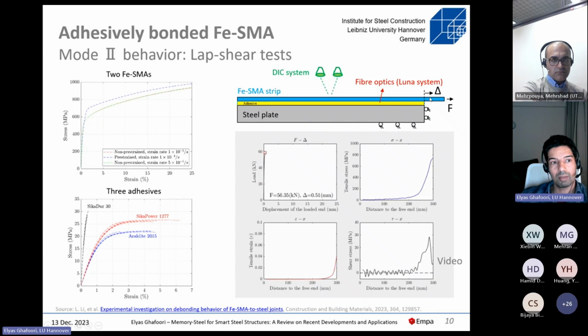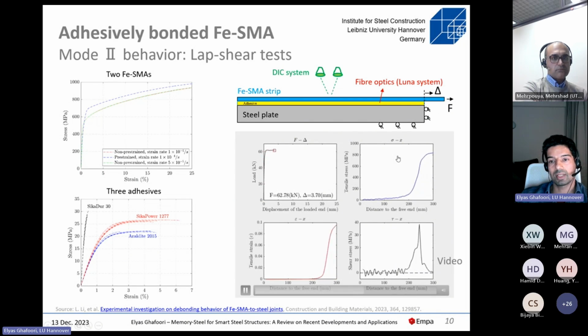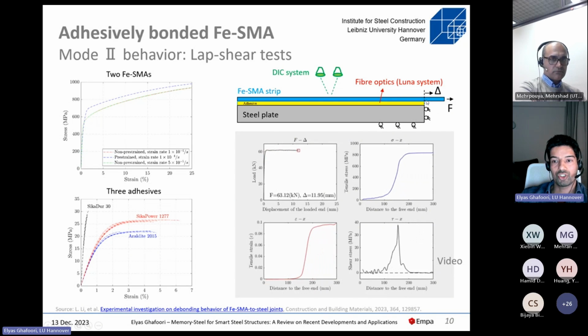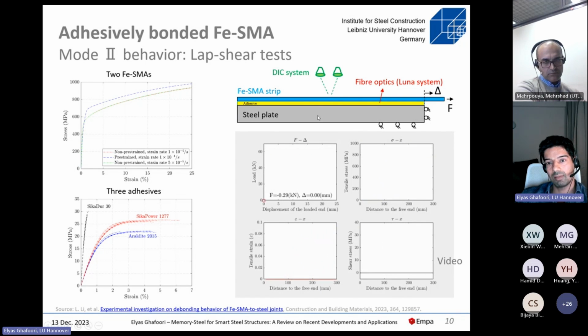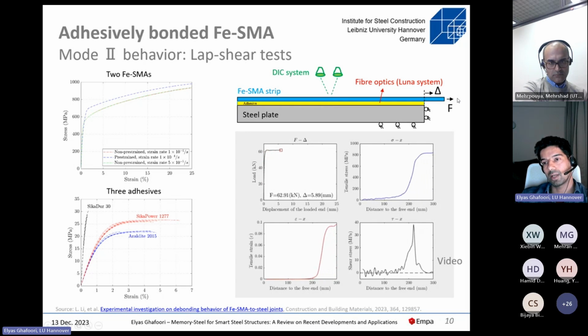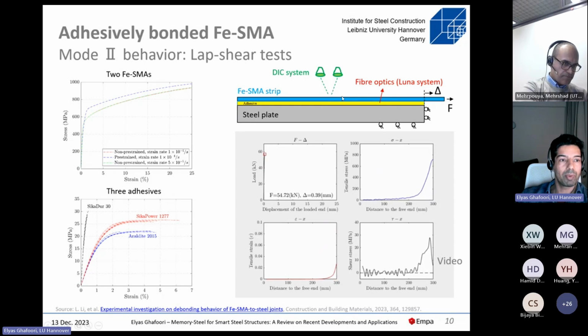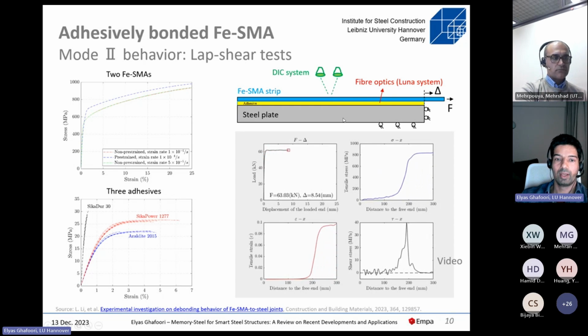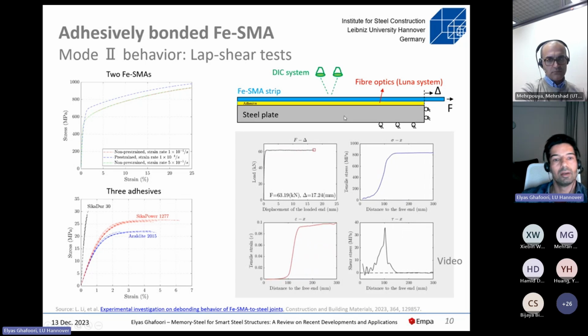Of course, the bond is very important here. So we have done extensive tests on lap shear tests. When this is a steel plate and this is an SMA plate, we bond that and we pull the SMA on the right side. And then we see how the debonding is propagating between the shape memory alloy and the steel plate. And from that, we can, of course, test different types of adhesives.